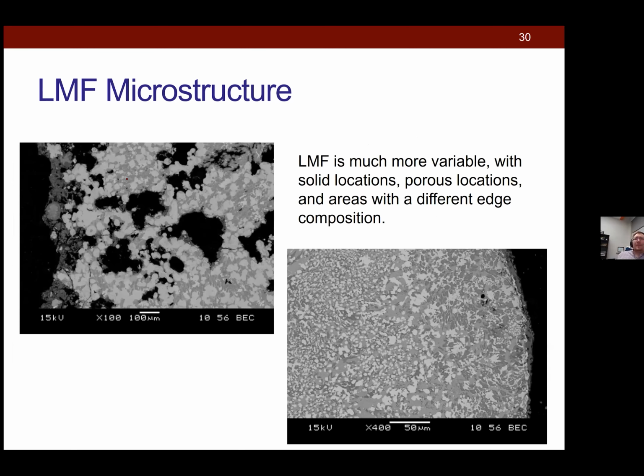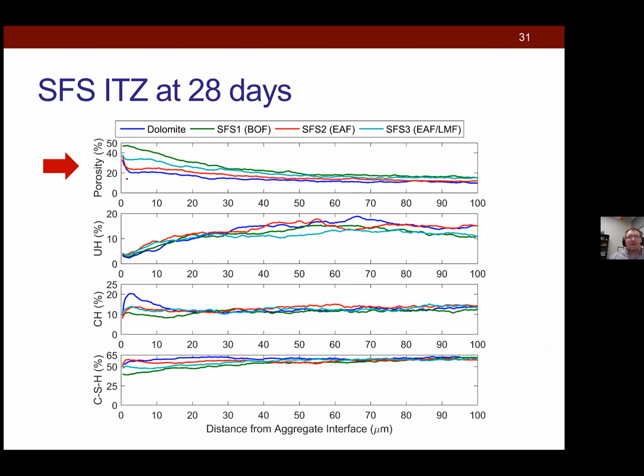So that's really probably why we saw a lot of reductions in strength with this material. And then this other slag type we looked at just had really variable composition. Some sections were very porous. Some sections had that same surface altered layer, whatever we want to call it. And other sections were very hard, condensed and fairly uniform. So a lot of high variability here. And when we then looked at the ITZ again, much like we did before, we did see some similar porosity distribution issues.